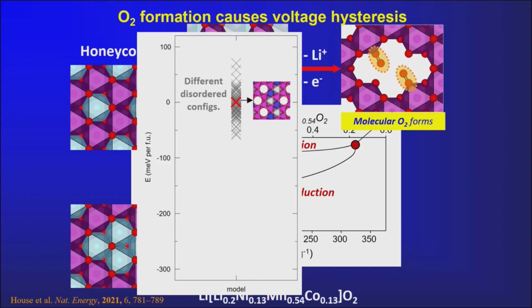So we can see that reflected if we do some DFT. Here's the DFT, the energy on the Y scale here. The crosses represent the energies of different arrangements of the vacancies created when you remove the lithium ions. So at this point, we haven't formed O2. We've just charged our material, and we're looking at how, if we reconfigure those lithium vacancies in different ways, you can get slightly different energies. But the real prize comes when you create a vacancy cluster, one of these, which allows O2 to be trapped. Then the molecular oxygens and the covalent bond, which is a big energy sink, drive the energy of this process down. It's this formation of the covalent bond which is really the driving force for this to happen.